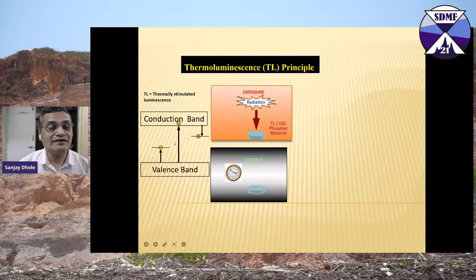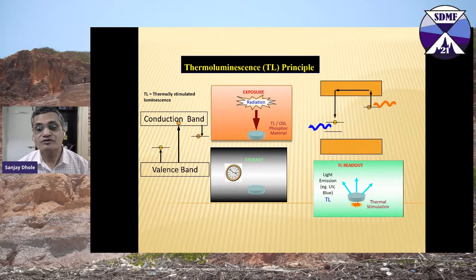So this is the conduction band, these are trapping levels, this is a hole trap, this is an electron trap, this is a direct band, this is band to band. This is the first one, the exposure of the phosphor, and this is the storage. Now we go for reading the dose. When you heat this nanophosphor, the radiation coming out is what the TLD reader will read out, and this is the mechanism where from the de-excitation you get the photon.